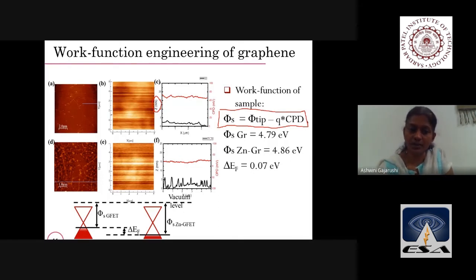Okay, so in this area, it has scanned around 200 times to get this image. This gives us around minus 60 millivolt of contact potential difference. When we use this formula, we get the work function of graphene as 4.79 electron volt. Now this D is the zinc modified graphene.